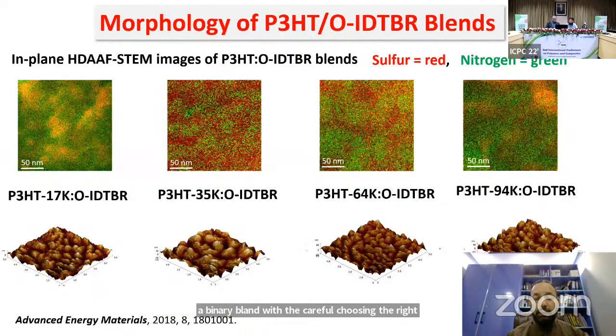To further test these things, we also looked into the morphology of these blends using transmission electron microscopy. If we see here, where the P3HT's molecular weight was around 35 kilodalton, both the donor and the acceptor components are well distributed and have smaller domains, compared to the very low molecular weight P3HT or very high molecular weight P3HT, where we can see big phase separations, which is not ideal for the best performance.